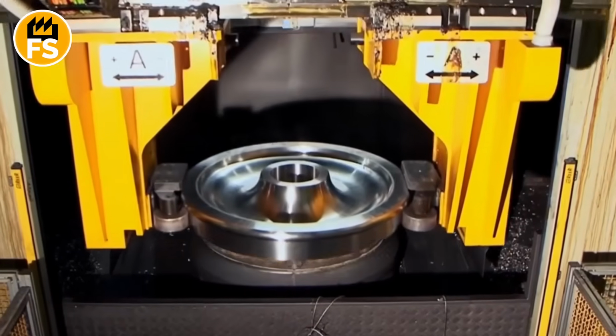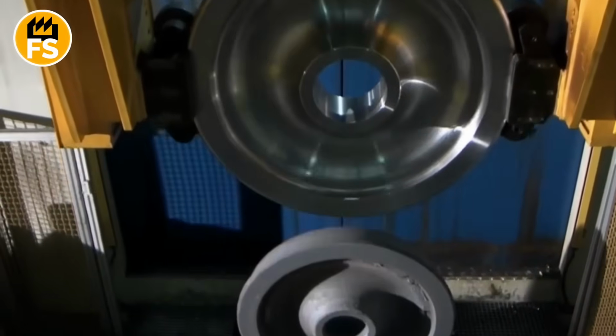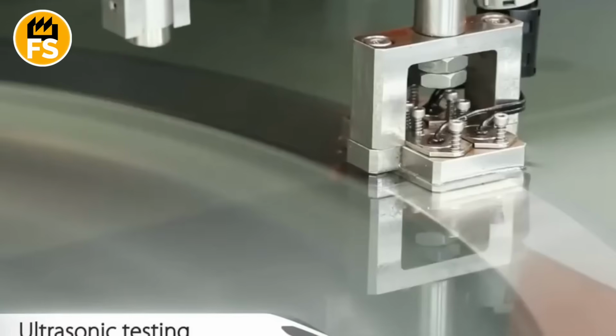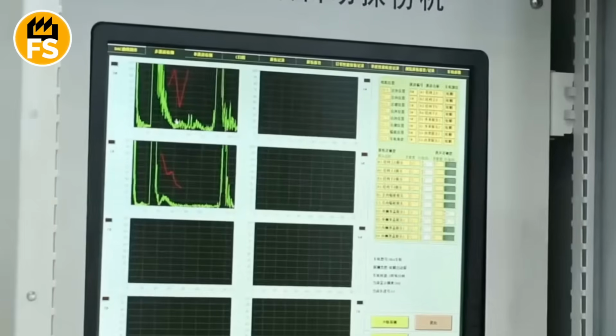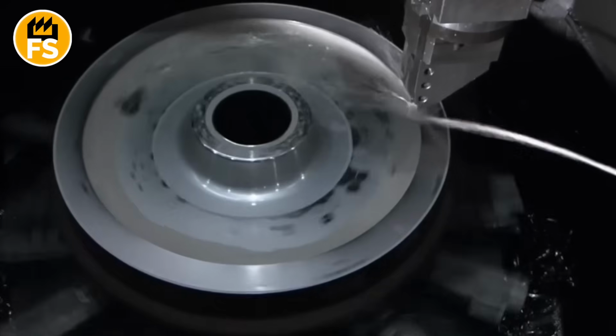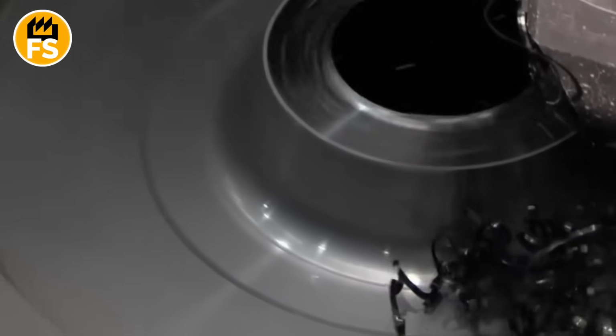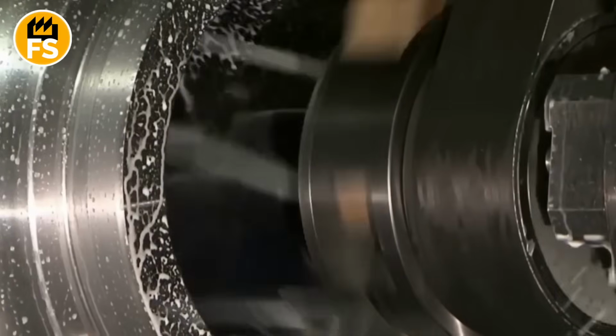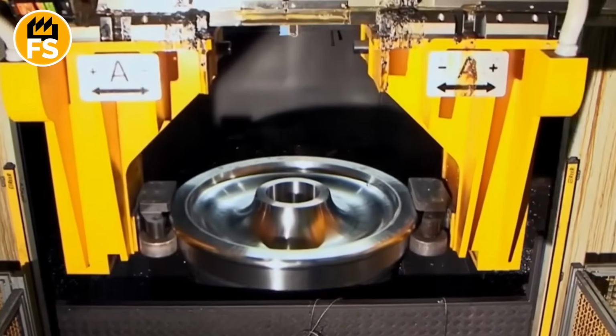But even after all these complex processes, no wheel reaches the rails without brutal yet necessary testing. Every single wheel, without exception, undergoes ruthless inspections. Ultrasonic testing. It's like medical ultrasound diagnostics, but for metal. Special sensors send high-frequency ultrasonic waves through the wheel. If there's even a microscopic crack, void, or defect inside, the ultrasonic wave bounces off it and creates an echo that the instrument captures. This method allows us to see internal defects without destroying the wheels. A defect the thickness of a human hair is already grounds for rejection.